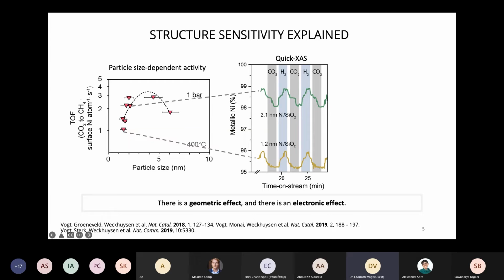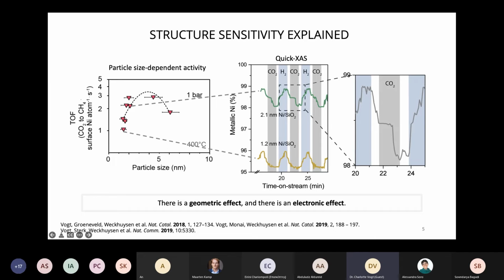There are two main reasons, which actually already stemmed from theory. One is that there's a geometric effect, basically the different types of architectures, nanoscale architectures, of those different sites. And the other one is an electronic effect. Once you go smaller and smaller in nanoparticle size, you start to feel, for example, the effect of a support much more strongly. And even below about 2.7 nanometers for nickel nanoparticles, you start to get things like quantum effects. Nanoparticles start behaving more atom-like, less metal-like, more defined band structure. Or not band structure, more defined energy levels actually.